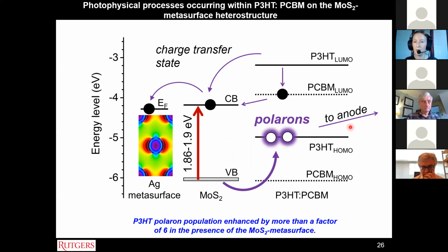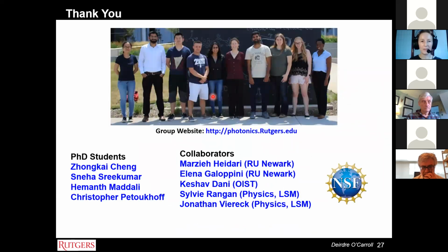This would mean that there would be a greater photocurrent in an actual device because we collect more polarons at the anode. So this is showing, proving then that we can improve this interface between the silver metasurface and the semiconductor polymer using this MoS2 interfacial layer for improving electron transfer. So I'm leaving it there, and I'm happy to answer any questions.